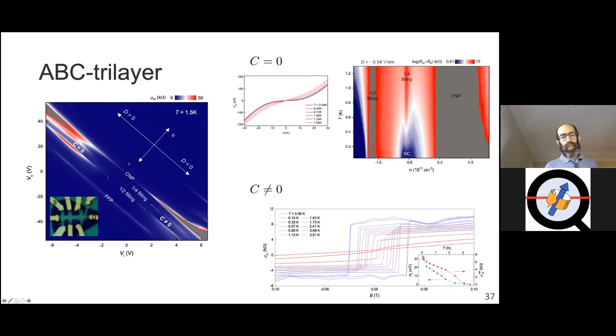It can be switched between different behaviors in a much more dramatic way than the twisted bilayer if we switch the displacement field. I'm not going to go through this in detail, but for one direction of displacement field, we get superconductivity. That's unlike the twisted bilayer aligned with boron nitride, where there's no superconductivity. For the other direction of displacement field, we don't see superconductivity, but we do see magnetism, and we do see these hysteresis loops.